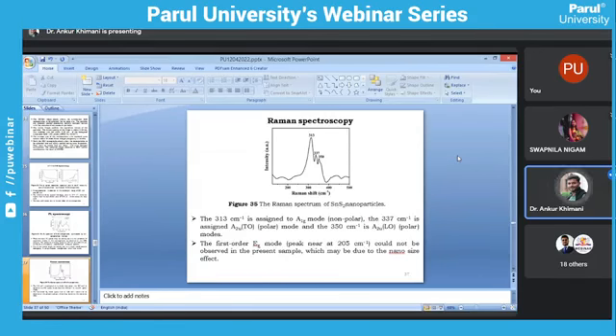First is 313 centimeter inverse, second is 337 centimeter inverse, and third is 350 centimeter inverse. The 313 centimeter inverse peak is assigned to the A1g mode, that is non-polar, and the 337 centimeter inverse mode is assigned to A2u, that is TO, transverse optical polar mode, and 350 centimeter inverse is A2u, that is LO, polar modes. The first order Eg mode peak near 205 centimeter inverse could not be observed in the sample, which may be due to the nano size effect.